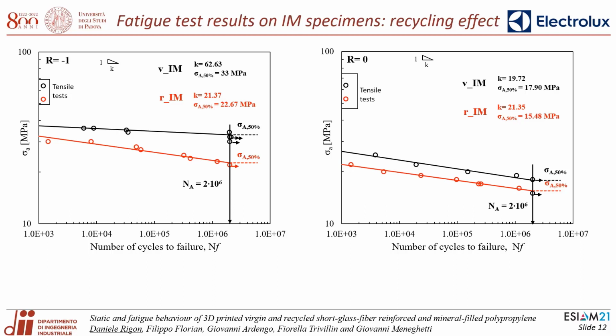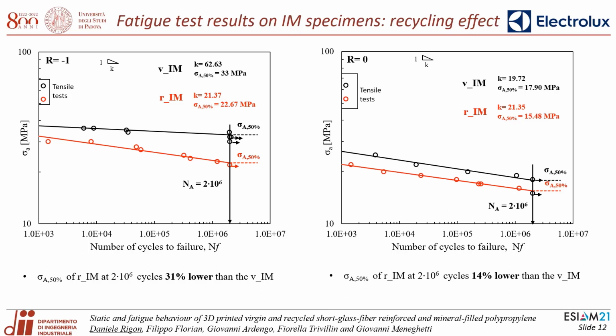In the high cycle fatigue regime, precisely at 2 million cycles, the fatigue strength of the recycled injection molded specimens is 31% lower than that of the virgin material for load ratio equal to -1, while for R equal to 0, the reduction is only 14%. Furthermore, the difference in terms of inverse slope K of the fatigue curve, statistically evaluated on the data, suggests different damaging mechanisms between low and high cycle fatigue regimes for R equal to -1, though this is not observed for R equal to 0.